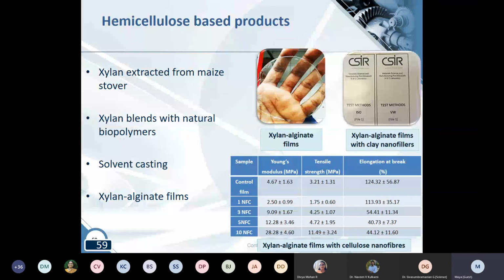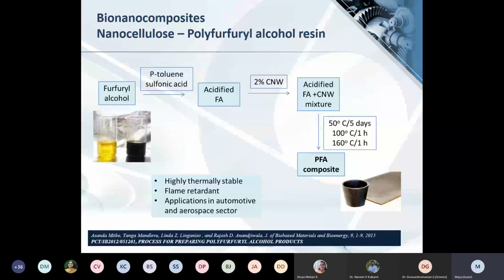So this is another example of where we developed a product from nanocellulose. Here the polymer matrix that we use was furfuryl alcohol, and during the polymerization of furfuryl alcohol, we added the cellulose nanowhiskers (CNW), and we got the PFA composite comprising of cellulose nanowhiskers (CNW). Now, as I mentioned earlier, polyfurfuryl alcohol is an important resin. One, it's a bio-based thermoset resin. Secondly, it has a highly cross-linked structure, so it has inherent flame retardance, which is very important. So it has applications in automotive and aerospace sector. Here, you can see that both the matrix and the reinforcement can be derived from waste. So it's a completely waste derived product.